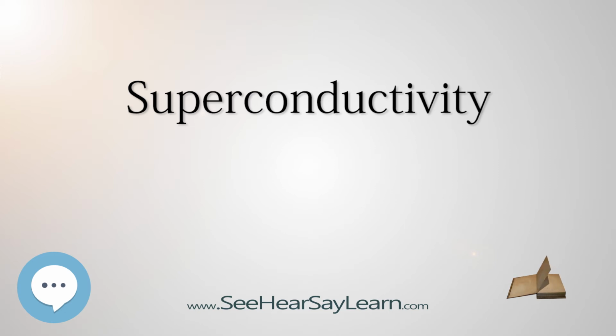There are currently two main hypotheses: the resonating valence bond theory, and spin fluctuation, which has the most support in the research community. The second hypothesis proposed that electron pairing in high-temperature superconductors is mediated by short-range spin waves known as paramagnons. Since about 1993, the highest temperature superconductor has been a ceramic material consisting of mercury, barium, calcium, copper, and oxygen, HgBa2Ca2Cu3O8+δ, with Tc equals 133-138 K. The latter experiment, 138 K, still awaits experimental confirmation, however.